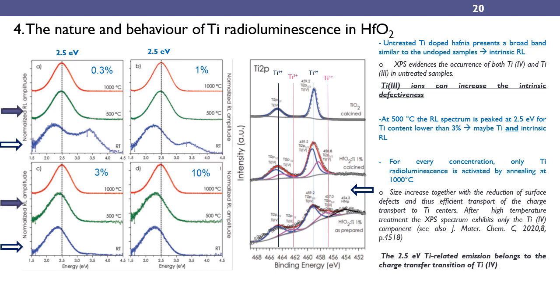For intermediate temperature close to 500 Celsius degrees, the spectra are peaked at 2.5 electron volt for low titanium concentration, and then they are shifted to lower energy. Despite the fact that this behavior is still unclear, we can consider that at this temperature, where a partial surface rearrangement starts, a competition between the intrinsic center and the titanium center is responsible for the change of the luminescence features.